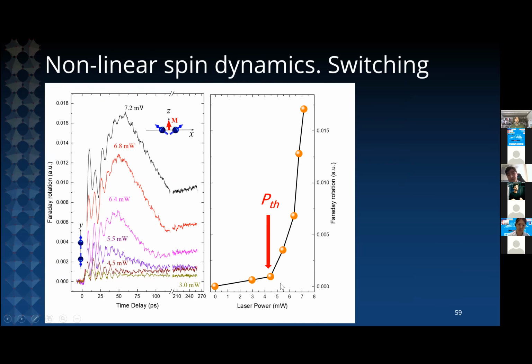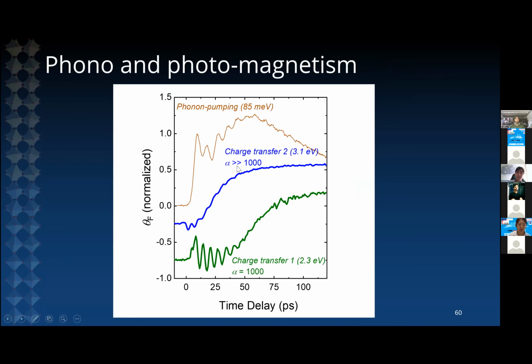And the threshold of this process is something of the order of 4.5 milliwatt. So what is the difference between this approach, which we call phonomagnetism, and the conventional photomagnetism? This is the same material being excited by a charge transfer excitation, as you see in green. And this is our phonon pumping approach that you see here. So indeed, when you excite the charge transfer, you do excite spin precession and then the emergence of a magnetization through a mechanism that I discussed before. But this relies on heating of the material, and it takes something of the order of 100 picoseconds to occur.